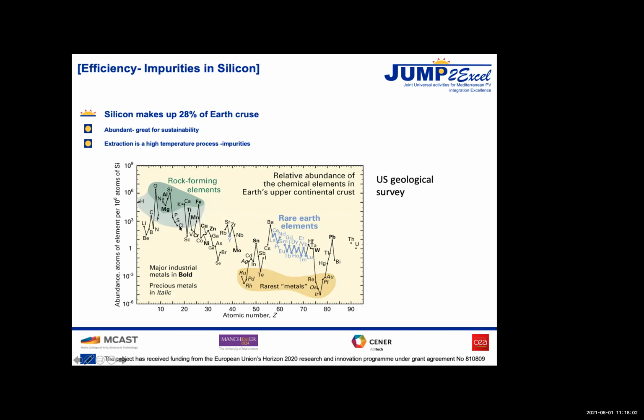Okay, but when you've done all that, you smelt silicon from sand, you're always going to end up with a load of other stuff in there, always inevitably. Also, all of these transition metals over here, so you're going to end up with iron, lots of iron, scandium, cobalt, chromium, nickel, all these things will turn up at very low densities, parts per million. But in a silicon solar cell, the electrons and holes you generate have to wander through, in atomic terms, a long way to get to their contacts. And if they encounter what we call a trap, which is a defect state that captures the electron, then the energy will be lost.